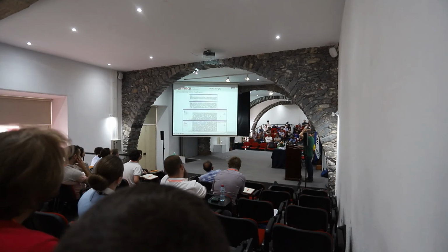Computational micromechanics came at a later stage, with faster computers and developments in modeling capability. So we started with the simpler fracture mechanics solutions, and eventually we were able to perform simulations, and the simulations are here. This is from the PhD thesis of Albertino Ortega, a former PhD student, now a colleague of mine. This is a 3D model, but you are just looking at the 90-degree ply, and we are loading in this direction.